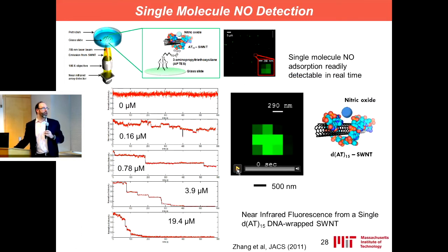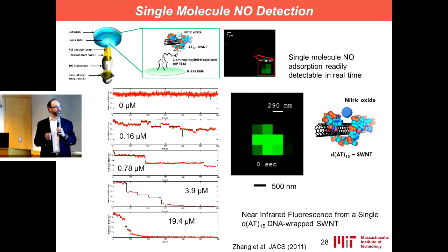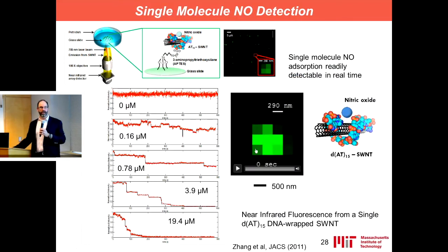oxide. Carbon nanotubes, like many emerging nanosensor platforms, have the ultimate detection limit. This is something I want to emphasize. Not just carbon nanotubes, but we now understand in nanotechnology that when you shrink a nanosensor down to a small enough scale, your detection limit falls as the cube of the characteristic length. So you eventually reach a point where there's no concentration below which you are unable to detect.